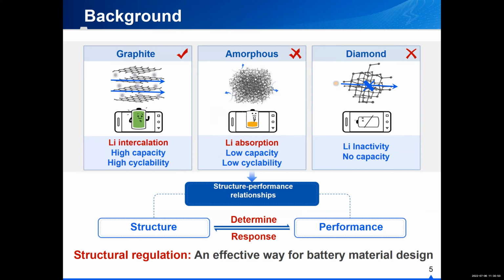Okay, amorphous carbon. Because it does not have a typical layer structure, it can only absorb or desorb lithium ions, so the capacity is very low and the stability is also very low. And diamond is another typical carbon structure, right? But this kind of material cannot allow lithium ions to get in and out of the structure because diamond is extremely stable. So this material does not have any activity, and there will be no capacity. So the structure determines the performance, and the performance responds to the structure. So structural regulation should be a very effective way for battery material design at any time, right?